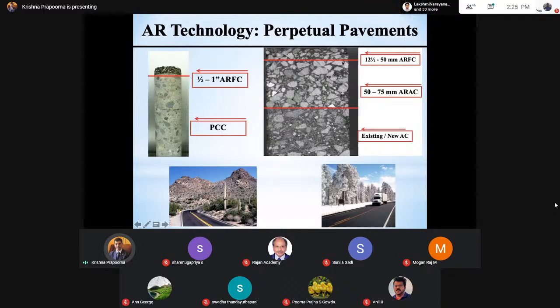Now the porosity of these top layers, surface wearing courses, can vary between 16 and 23%, 24% also is possible. These gap graded structures can vary anywhere between 7 and 11%. That's the porosity. Dense graded, you people are familiar, it can vary anywhere between 4 and 7%. In fact, even the IRC specifies 3 to 8%, which is the ballpark that we have.